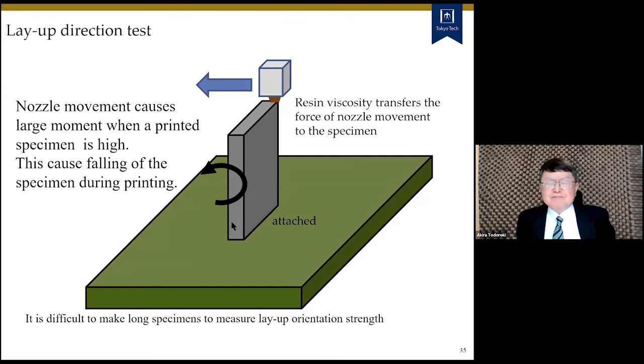And many research articles cannot measure the layup direction, because if you want to fabricate the specimens like this, we have to make the tall specimen, but with the nozzle movement in this direction, a large moment is applied to the specimens because the resin viscosity transfers the force of nozzle movement to the specimens in these directions. So this causes the moment. So this attached area is detached, so this specimen is falling. So it is quite difficult to make the long specimens to measure the layup direction strength. So many research papers did not measure the layup direction strengths.